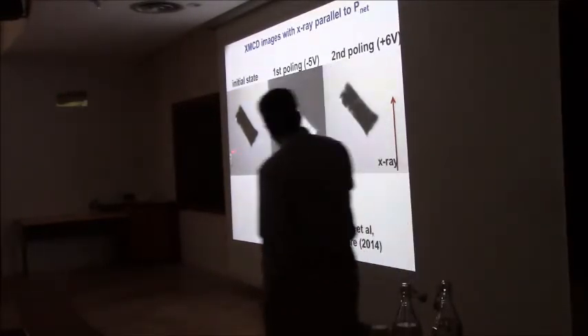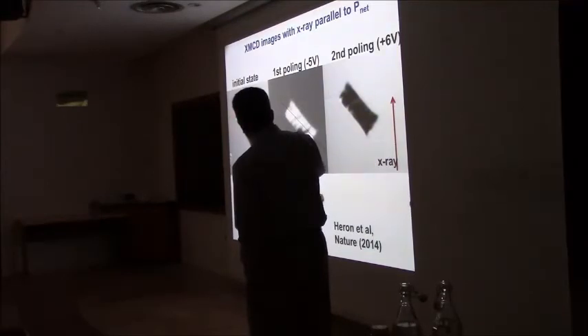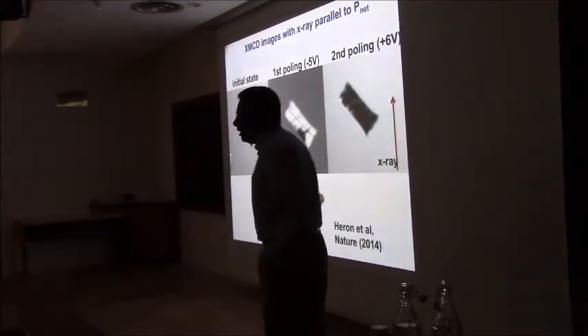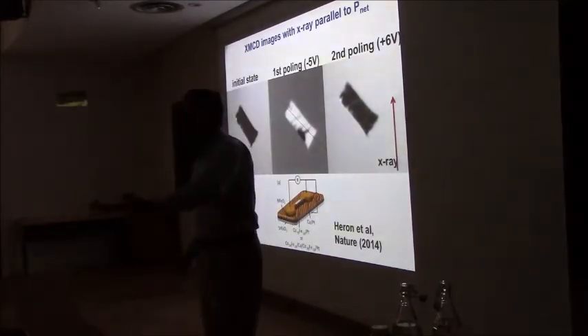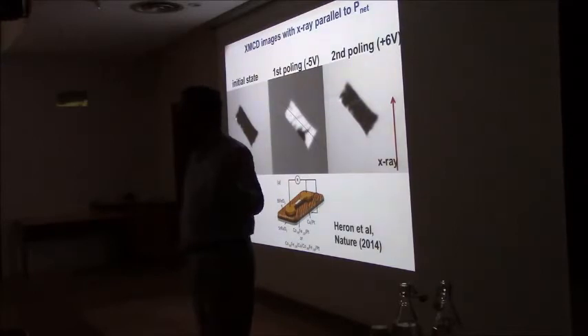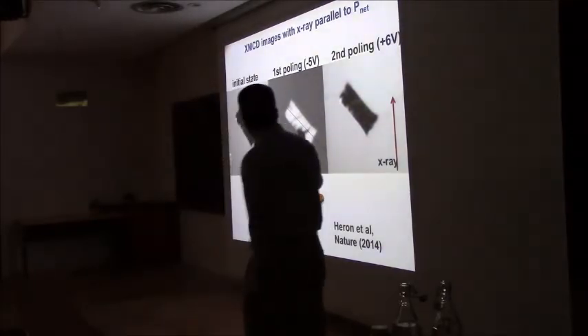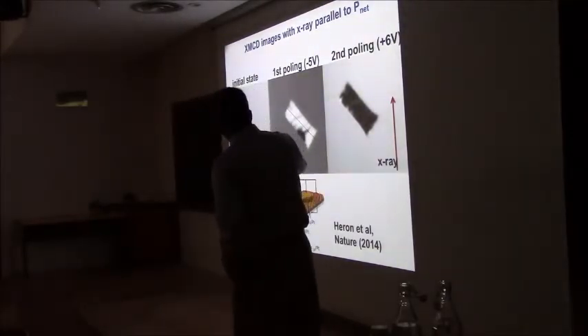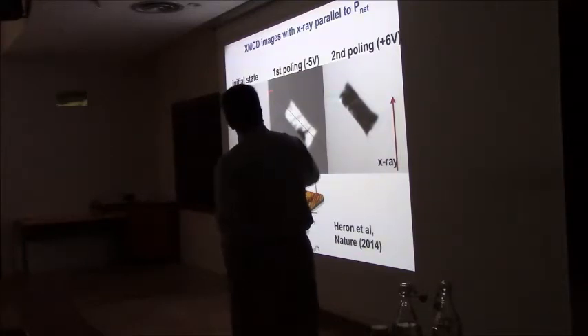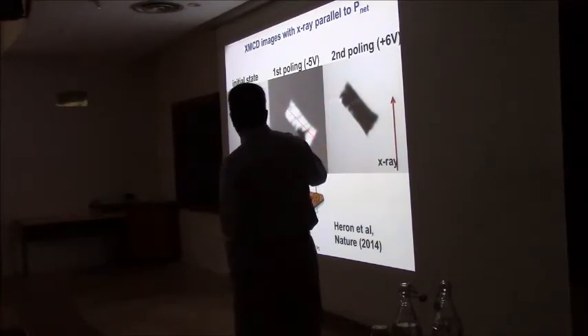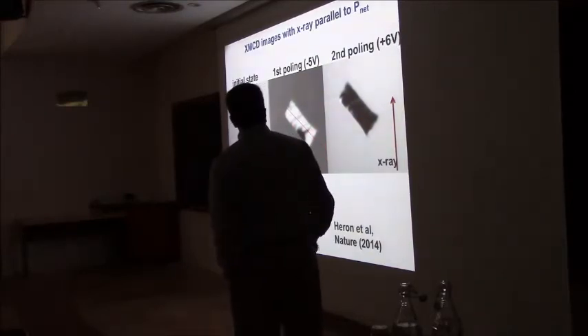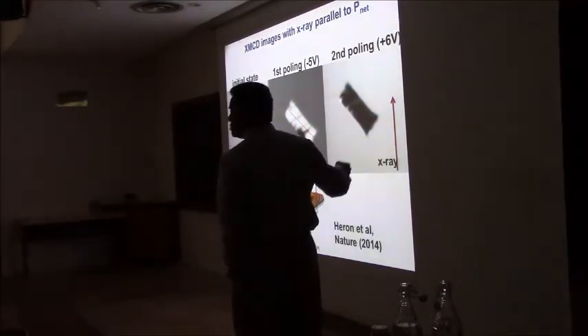The experiment was to take an island, and this is by a few microns. You can barely see the metal contacts. We wanted to image it in the as-grown state, look at what the magnetic structure was, and then come back, electrically switch it, and see what happens. That's the experiment. So initially it's the black state, for example, with the X-rays coming in this way. When you switch it with -5, it became essentially white with some remaining regions. You switch it back, it goes back to the black state.